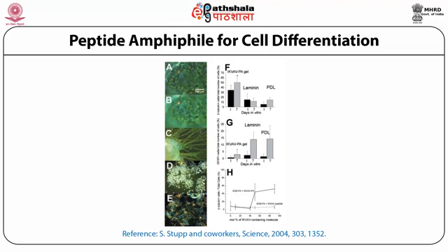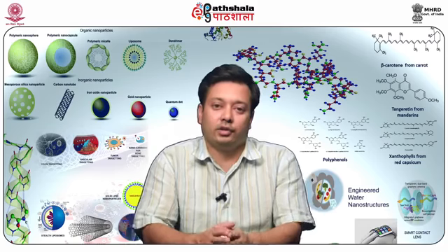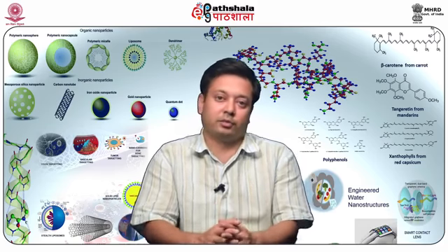But you can see that for laminin and other systems, it is mostly astrocytes or glial cells that get expressed. It is also important how much percentage of IKVAV containing molecule should be doped into the gel. You can see that beyond 40% of the IKVAV based polypeptide amphiphile, you can have better cell differentiation in the hydrogel medium. So let's summarize what we have learned from this module.